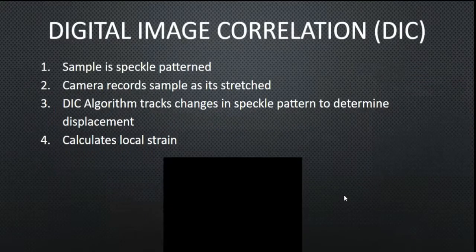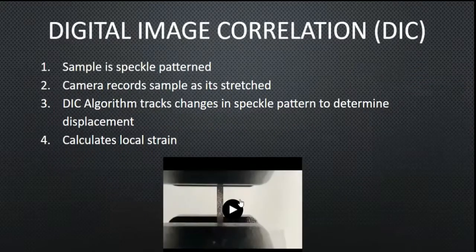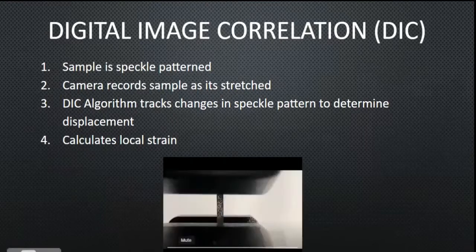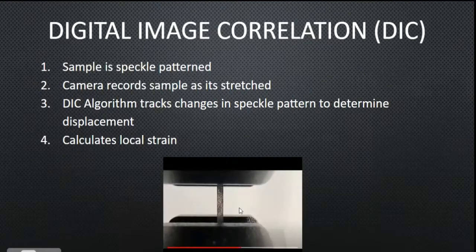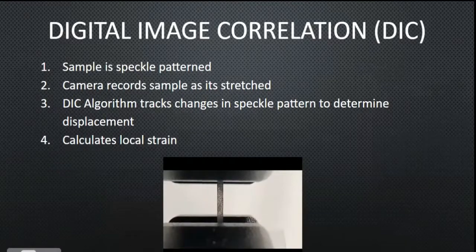Lastly, we did digital image correlation, and I have a video of it right here which explains it best. Basically, we speckle-patterned an LCE, then stretched it under the INSTRON and recorded it over time. A DIC algorithm tracks the changes in the speckled pattern over time as the sample is stretched. This change leads to a calculated displacement and thus the local strain at each point within the LCE. You can see the speckled pattern changing in this video.